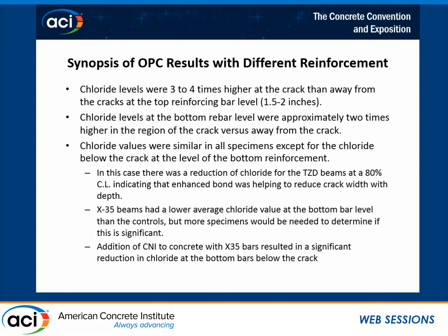The chloride levels at the bottom rebar level were approximately 2 times higher in the region of the crack than away from the crack. So even though the cracks are pretty much being stopped a little bit below the top bar, the effects of that crack are being seen farther down.